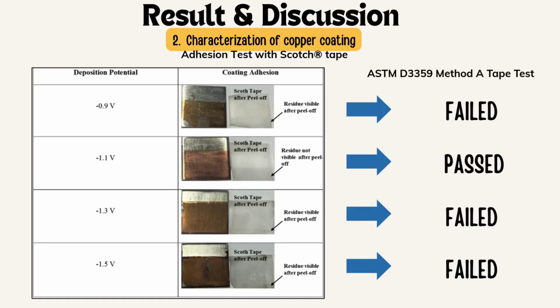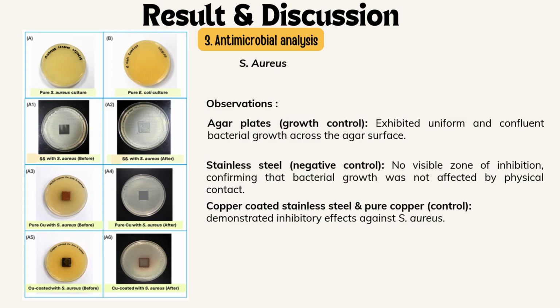Next is the adhesion test. The tests were conducted in accordance with ASTM D3359 standard. The results showed that only the copper coating deposited at negative 1.1 volt displays excellent adhesion and no residue after the tape has been peeled off. Lastly is the antimicrobial analysis.